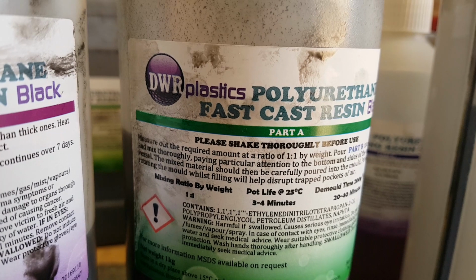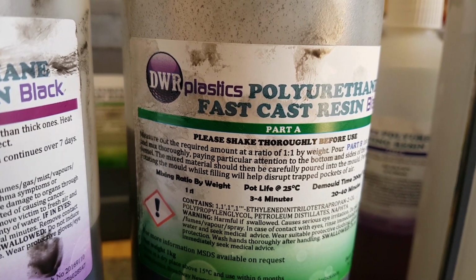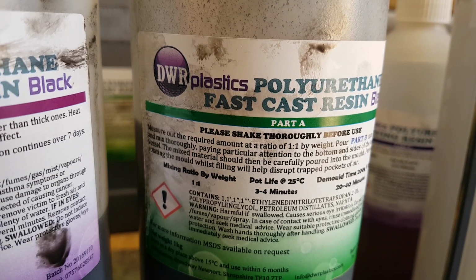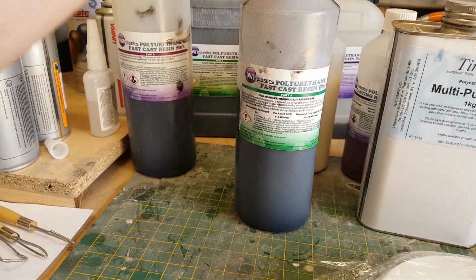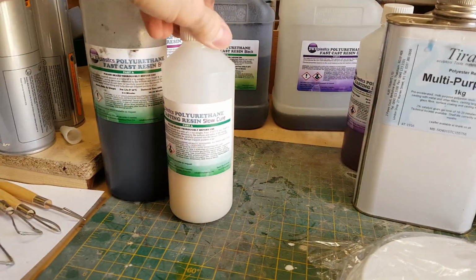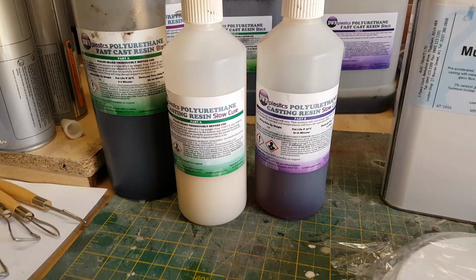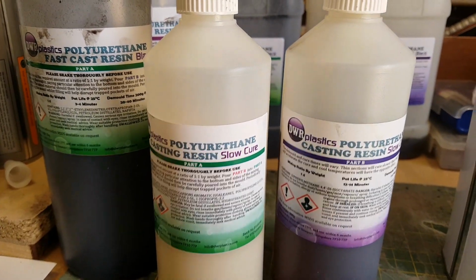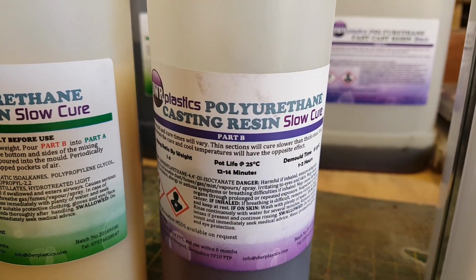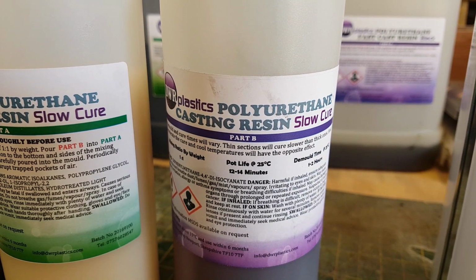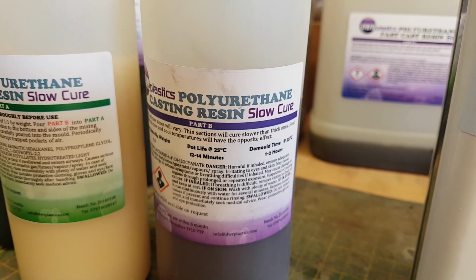In the case of the polyurethane resins, this is a fast cast resin, and as you can see it's going to cure in 3 to 4 minutes. But there's also a bunch of other versions of this as well. So this one here is a slow cure resin, and as you can see it's got a pot life of 12 to 14 minutes. And the reason for that longer life is so you can actually pour your resin and then put the mold into a pressure chamber to get rid of air bubbles.